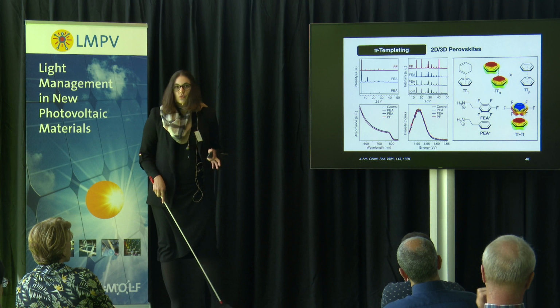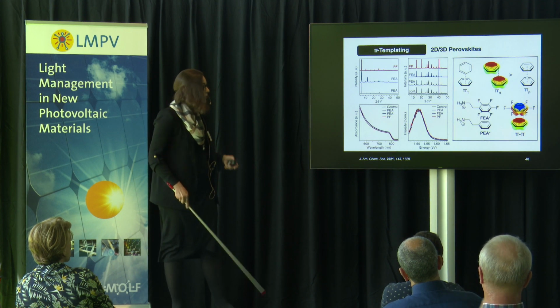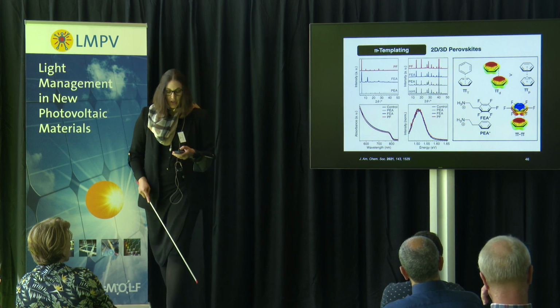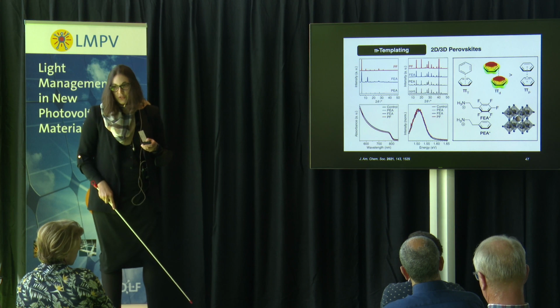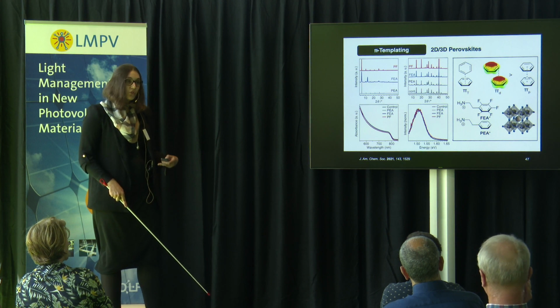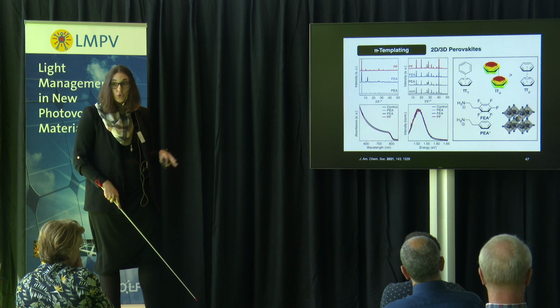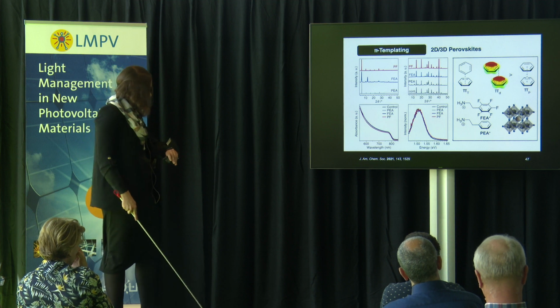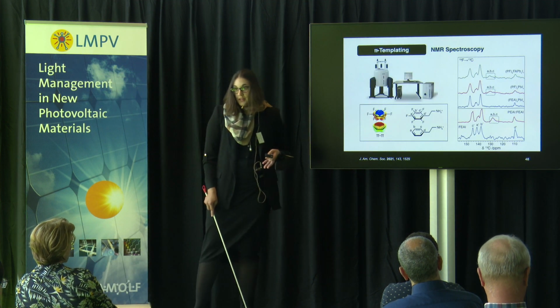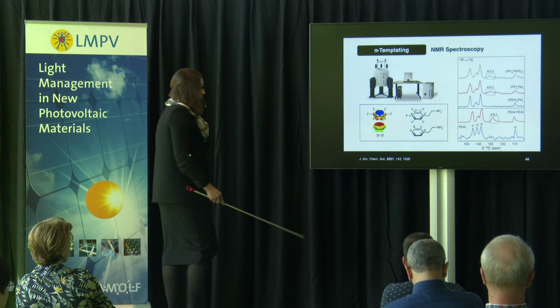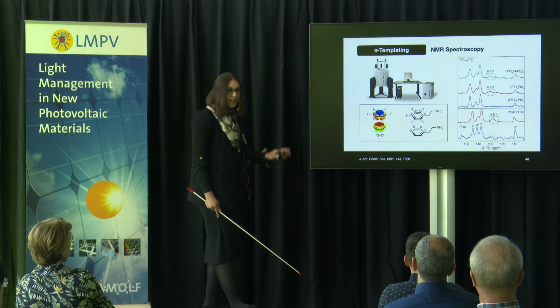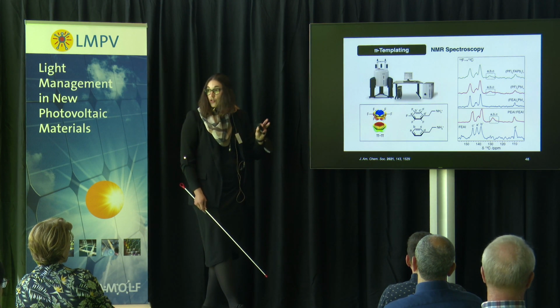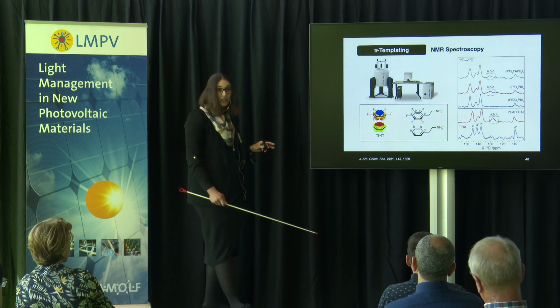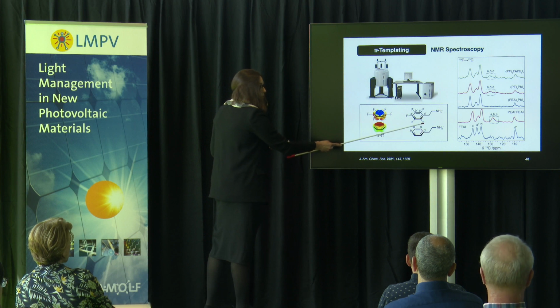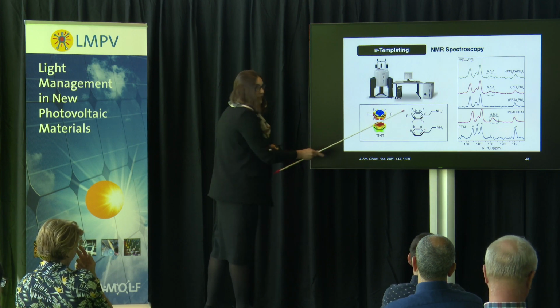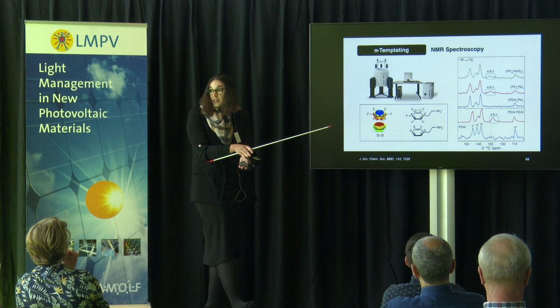However, in this case as well, it is important to realize that when we use typically X-ray diffraction for the analysis of these systems, we still analyze primarily the inorganic phase. So in order to truly understand the importance of the organic components within these systems, it is much more important to complement this analysis that is conventionally done with the perspectives from NMR spectroscopy that I want to highlight on this occasion. And for this purpose, the presence of some of the elements like fluorines offers not only a gauge to control the assemblies, but also a label to follow some of these interactions. And in this case, by monitoring once more these exchanges in polarization between the fluorine and the carbon that can take place only within their nanoscale proximity, such as when forming these pi-based interactions.